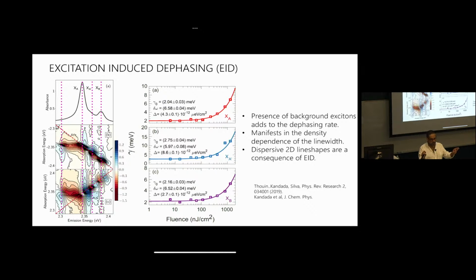You have the same quantum confinement and dielectric confinement effects, but it's a covalent system, right? And so if I measure these deltas for molybdenum diselenide, I find that there's a difference of about 100 to 1,000 in the scattering rate, in the density-dependent scattering rate, what's called excitation-induced dephasing. And that is because here you have a very strong effect of the polaronic protection.